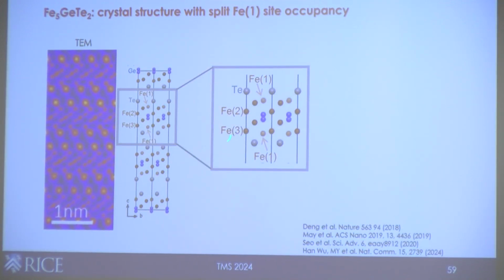If you look at one of these slabs, you'll notice this is inversion symmetric. And the inversion center lives between these two blue sites. These are germanium split sites. Everything comes in pairs about that inversion center. You have a tellurium pair. You got 2 iron pairs, so these are all fully occupied. The last remaining pair is iron 1 sites, and if you have exactly Fe5, then between each up and down site, you can only occupy one of these 2. So that's the key thing in this material.